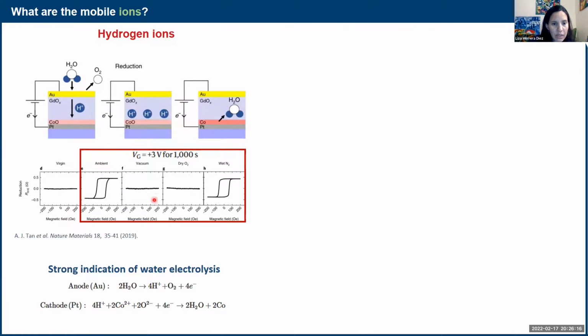You can see very well here that they start from the virgin sample, and then in ambient conditions, they get a large change in the anisotropy. But if they do it in vacuum, there's nothing going on. If they do it in an oxygen atmosphere, but dry oxygen, there's nothing going on. And even in a nitrogen environment, but with a little bit of water, then they could see something. So it's fundamental to have water.